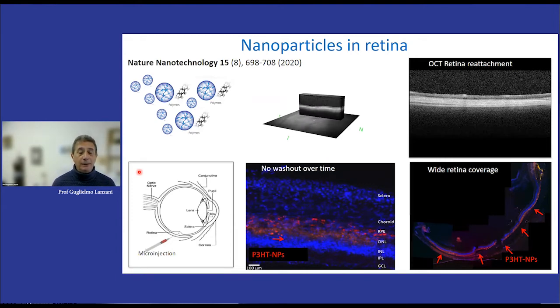You see that the optical tomography shows a perfect retina. So the retina is fully reattached, and the nanoparticles stay there over time. So what we can say is that after 8 months, the nanoparticles are still there and they are still working. And the coverage of the retina is now in the order of 70-80%. So it's much, much larger than what we had with the planar prosthesis.